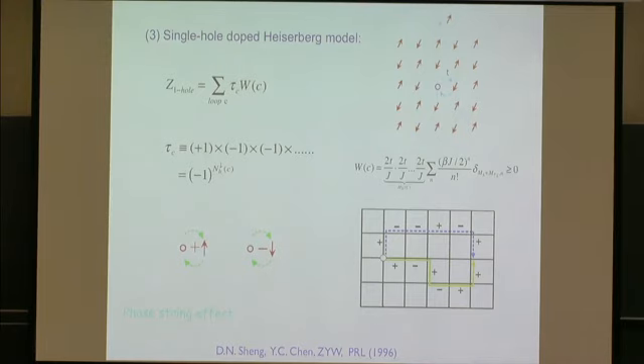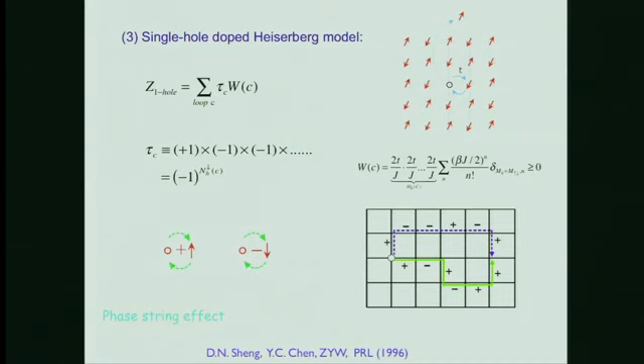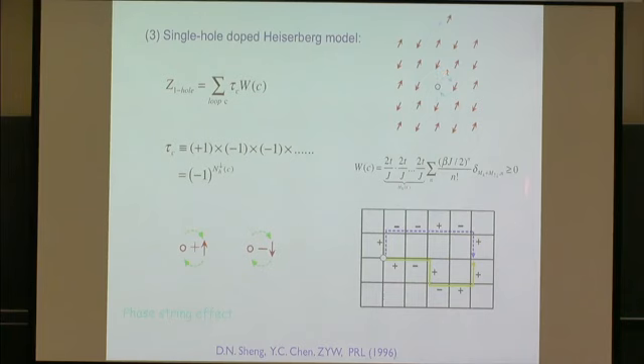Okay, now let's dope this system by taking one electron out. So suppose we just consider one hole. Then the hole can start to move because a spin can jump to this side. And then you find that the partition function will have some actual path associated with the hole's motion, and this path will have some sign come out. This sign is basically a product of plus and minus signs, depending on whether the hole exchanges with an up spin or a down spin. So this sign just differentiates two different kinds of polarization.